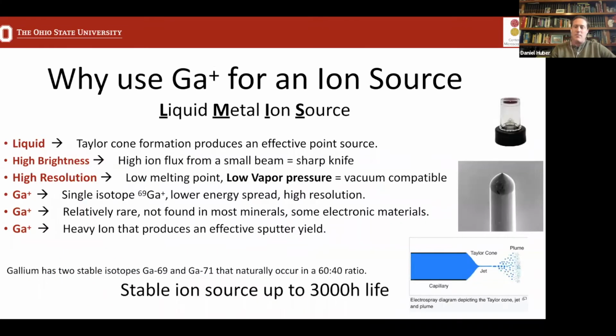So in our 2 FIBs, we have liquid metal ion sources. So the question is, why do we use gallium? Why is gallium a good source for the FIB? And the main attraction for it is this phenomenon that's called a Taylor cone that's formed at the end of the needle. So it produces a very sharp, effective point source of ions. That sharp source gives us a very high brightness. It's like cutting with a sharp knife.